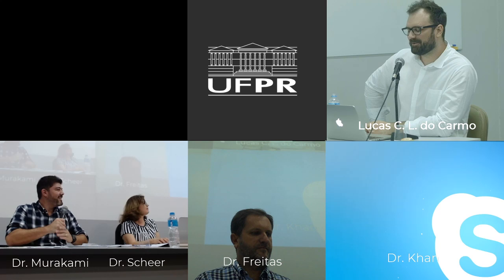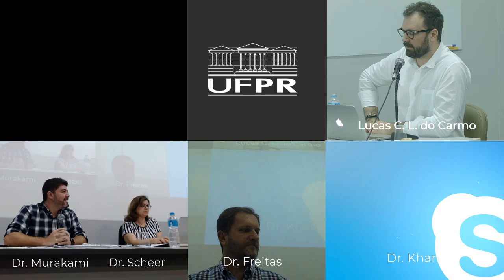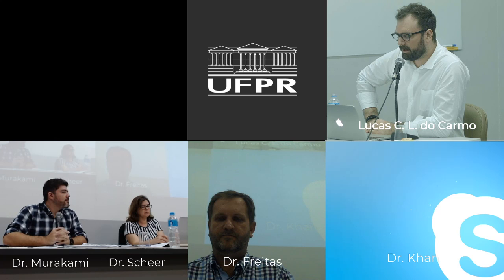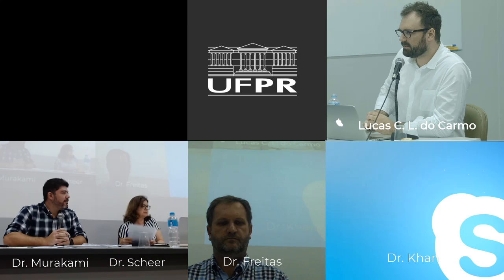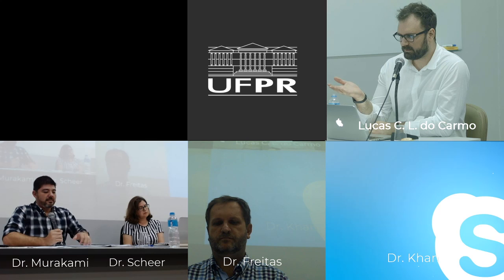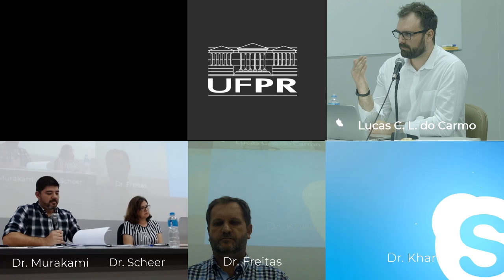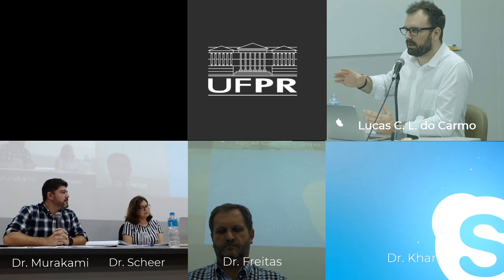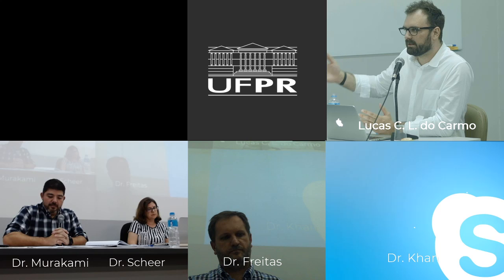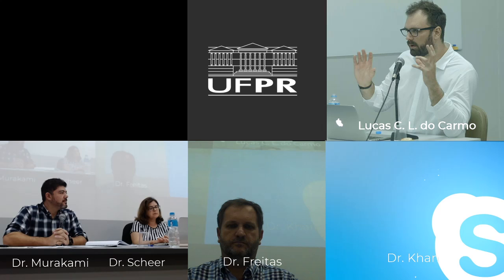Well, in the presentation I showed you like 8 references about this methodology. I think that it is still too early to say. However, I believe that there may be some signs that it can be used. Now, Brummer, in his book in 2006, published a large-scale study with hundreds of formulations, both of the cosmetics and food industry, where he found that formulas that had a higher variance of G prime and G double prime in higher temperatures destabilized a lot faster than the ones who had no variance on these values over temperature.